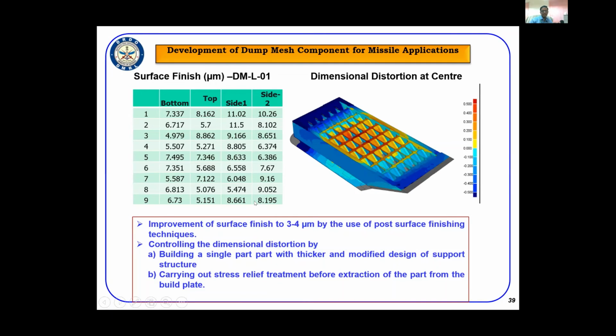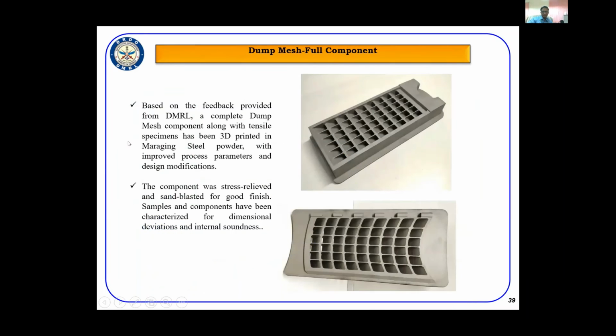So these are the 2 additional measures we have taken from this analysis of the dimensions, and based on the feedback provided from DMRL, we could go ahead with the complete component along with the tensile specimens, with improved process parameters and design modifications. Then the component was stress relieved and sandblasted to a good surface finish, and we could realize a very good component which is meeting the dimensional requirements, and also in terms of soundness, that means the porosity is found to be very, very low.